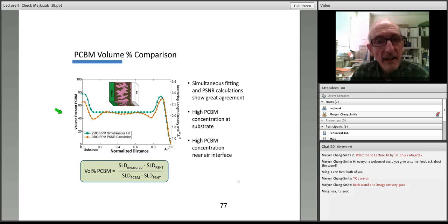Now, it turns out that lots of people have a preference, instead of doing the direct inversion solution of the real part of that reflection amplitude that's obtained, to just take the two data sets and simultaneously fit them. And if you do that, it turns out it's a bit more work, and it takes more time. But the fact is that having those two composite data sets is equivalent in its content of phase information, and nothing is different about what's there.